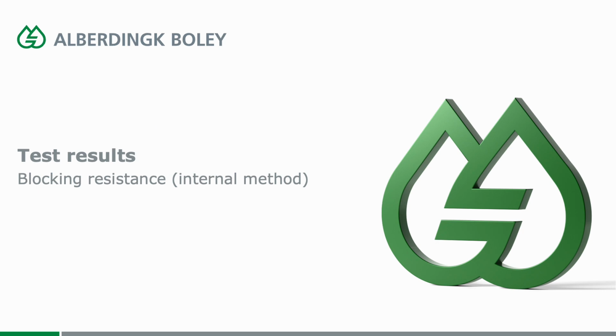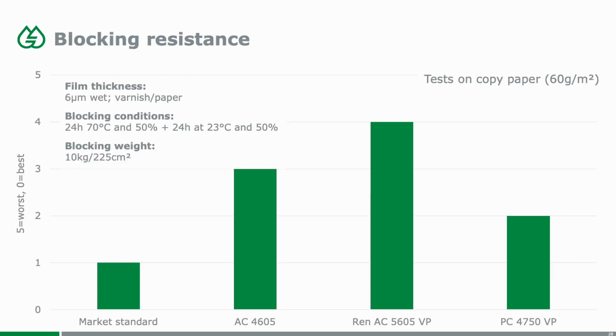Since paper which is coated has to be wound up on a roll, we also test blocking resistance. That is according to an internal method. So blocking resistance here is tested 6 microns wet. You test varnish versus paper, which makes sense because you roll up on a roll, and the face of the varnish will stick to the paper. The blocking conditions are 24 hours at 70 degrees centigrade at 50% humidity, and after that you block it for 24 hours at 23 degrees and 50% relative humidity, and you apply a weight of 10 kilograms per 225 square centimeters. And the lower the column, the better is the blocking resistance.